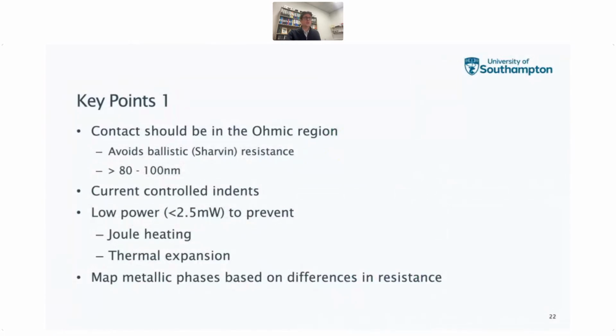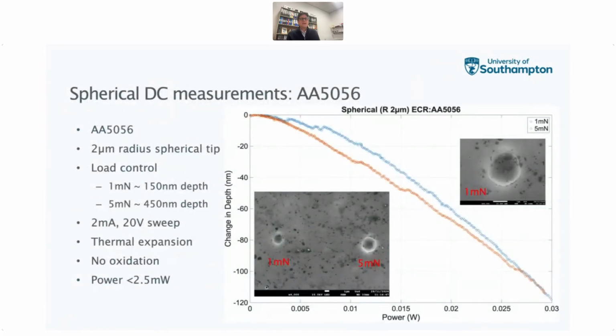So just to summarize those key points, if you're going to attempt this, you probably want to be in the ohmic region of the contact to avoid any of this ballistic or Sharvin resistance component. So it's really higher than about 80 to 100 nanometers in this case. We'd recommend current controlled indents for this type of contact, but you really need to do that at quite low power to prevent the Joule heating and thermal expansion effects that we've seen. But then you can start to map different metallic phases based on the differences in resistance. Now, the premise really was to try and correlate this with the metrology, with the phase topography information. Could we do that with the resistivity, with the resistance measurements?